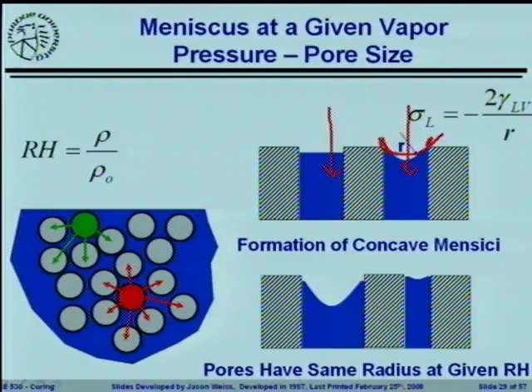And the big implication of this meniscus that's forming is it's going to be directly related to the amount of stress that's forming inside of the fluid, the under pressure that's forming in the fluid. So the stress that forms, sigma L, is going to be equal to 2 times the surface tension of the fluid at the liquid-vapor interface divided by the radius. Now when we talk about this, we're talking about the pore radius, the distance between some of these particles. There are a lot of assumptions and approximations that go into this, but the basic thing you can start to see here is that the stress that develops in the system is inversely proportional to the radius.